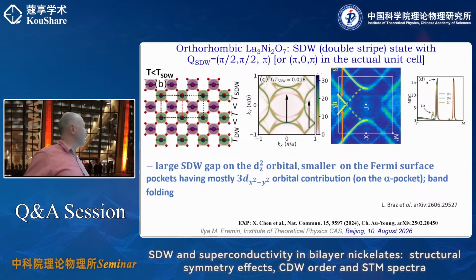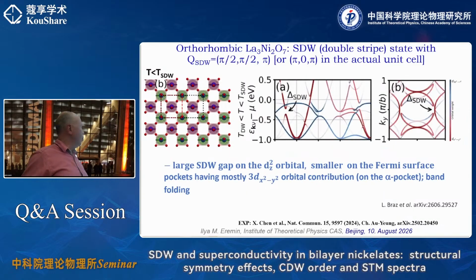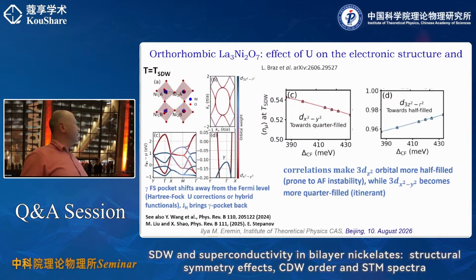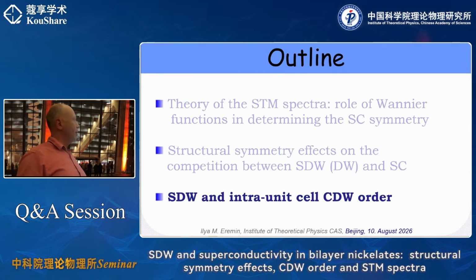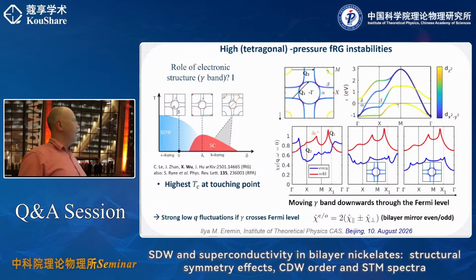Here, it is an odd susceptibility. So here we say this is an odd susceptibility because effectively what is needed is that you have a large separation between them: the odd susceptibility is much larger with these wave vectors than the even susceptibility. Sorry, I need to remove this one. Yeah, because effectively it's not a purely interlayer exchange. So it's basically, you see, the difference between intralayer and interlayer. But effectively, you work in the situation when interlayer antiferromagnetic fluctuations are stronger than the intralayer.